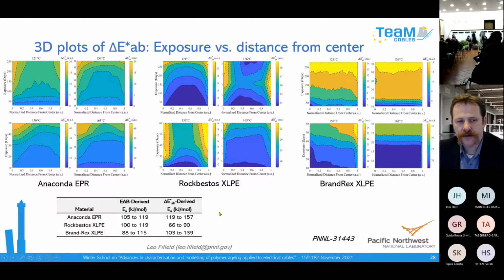And one of the goals here, which worked reasonably well, was to try to compare normal activation energy. The normal process for calculating activation energy is often done with tensile elongation at break, and we compared that with the activation energy you might calculate if you're just looking at the interior of the cable material. So if this DLO artifact of accelerated aging is really throwing off your lifetime prediction, then you might be able to see that if you predict the life from the interior of the cable versus the exterior of the cable.